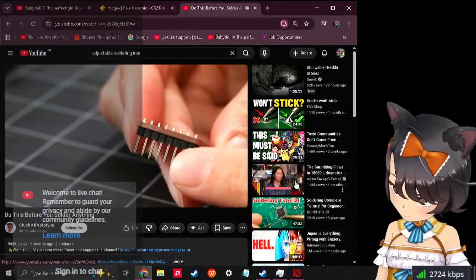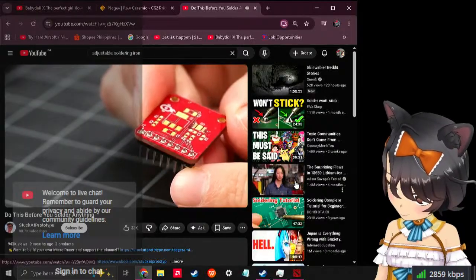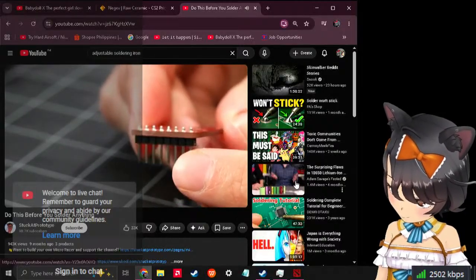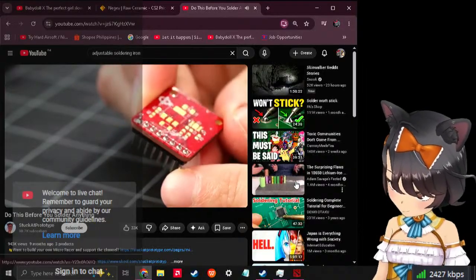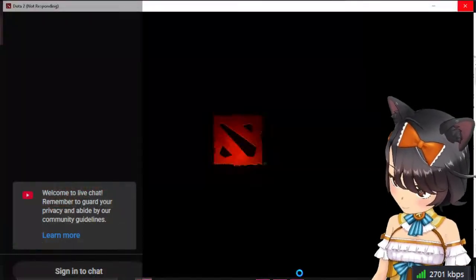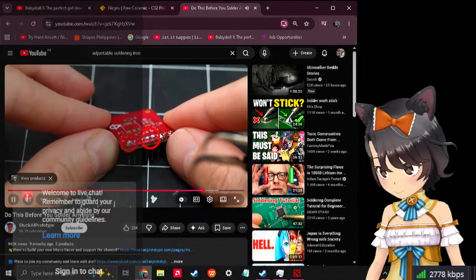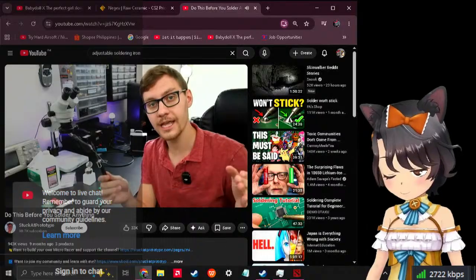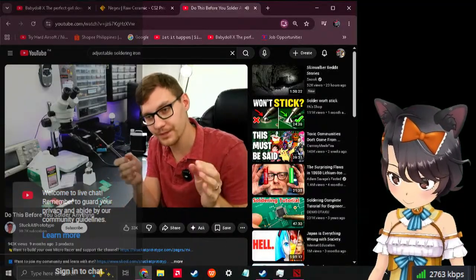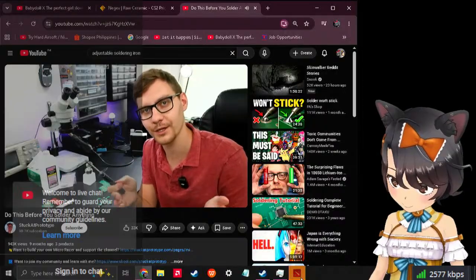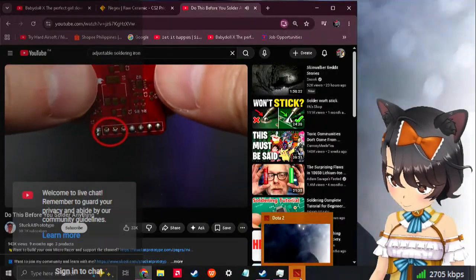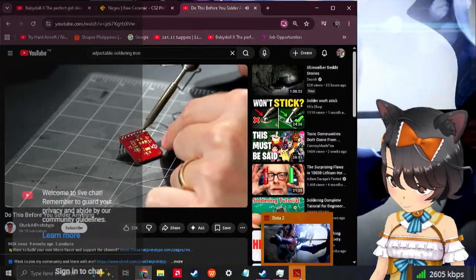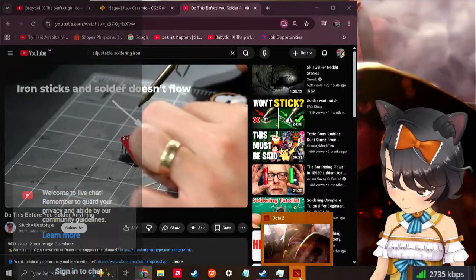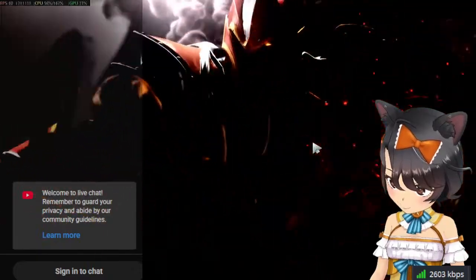So once you've actually fed the solder into the joint, you're looking for this beautiful bell-like shape, a reverse bell I guess you could call it, and you're looking for a shiny, nice surface. If it is bulging to the outside, that means you fed too much solder. If it is looking empty or has a hole, it's basically a starving joint, right? There's not enough solder. Add a tiny bit more. And if it is misshapen and just odd looking, not a beautiful shape like this, that means it is probably a cold joint. Good news, it is easy to fix.